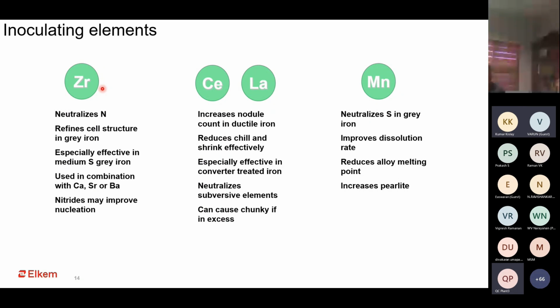Then again, in low temperature casting, low temperature foundries where the metal temperature cannot go very high, they may face some problems of dissolution of inoculant. A manganese based inoculant helps you there because it reduces the melting point of the inoculant. So thereby it ensures that your inoculant dissolution improves even at a lower addition temperature.